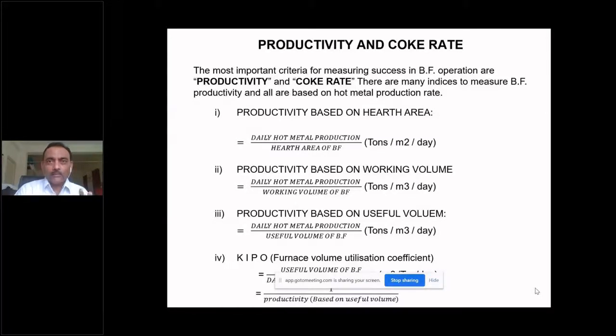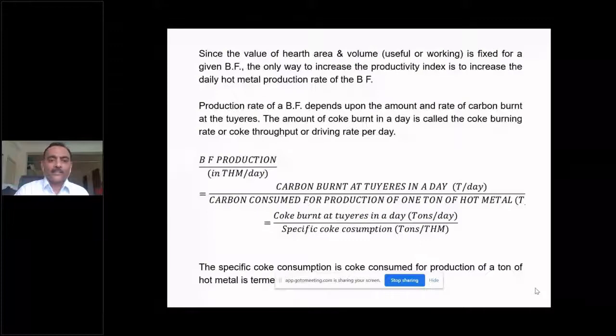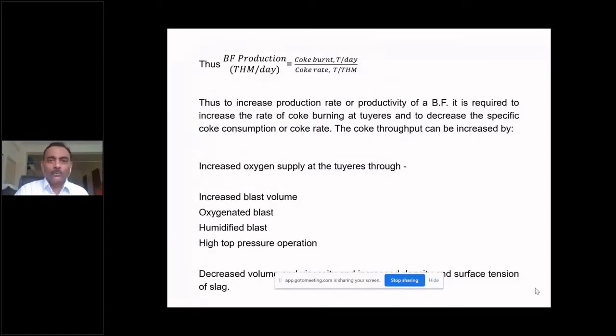Okay, I have to look about my heat value, because from coke heat will come, from hot blast heat will come, from coal dust injection heat will come. So I have to counteract. But if somehow I am able to reduce the coke part for 1 ton of production of hot metal, quite naturally, again my productivity will improve, because my production will improve and coke rate is reduced. So in the process of making hot metal from the blast furnace, if we are able to reduce coke rate, naturally productivity will improve. They are both inversely proportional. These are some definitions and how it will improve.